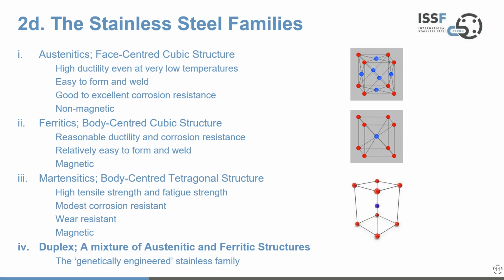The martensitic group are really a stretched cube. It's a body-centered tetragonal structure, so similar to the ferritic, but just, as I said, a stretched atomic structure. Here you get a high tensile strength and good fatigue strength, relatively modest corrosion resistance, as I've said. One additional benefit is wear resistance in this family of grades. And as the ferritics are, they are magnetic.